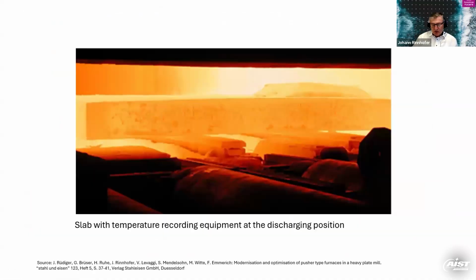And this is how the slabs looked. So we are measuring the temperature here with this little box which is sitting on the slab here. You see a little bit of scale here. Actually, when you look into a furnace, when you look at the scale with the pyrometer, it usually shows a higher temperature than the slab, because it's brighter than the slab. When you come out with the slab onto the roller table, the scale will cool down and it will show a lower temperature actually. So you measure a lower temperature when you look at the scale outside the furnace, and you measure a higher temperature when you look into the furnace at the scale. And so you have to be careful what you measure when you look with a pyrometer.